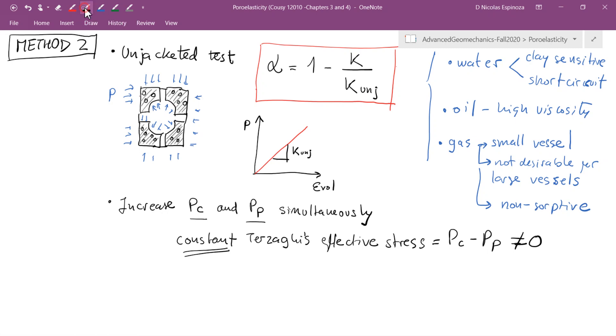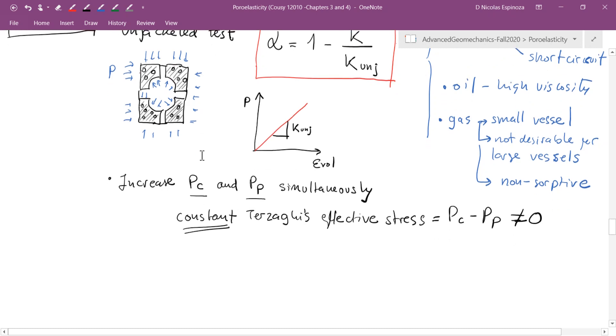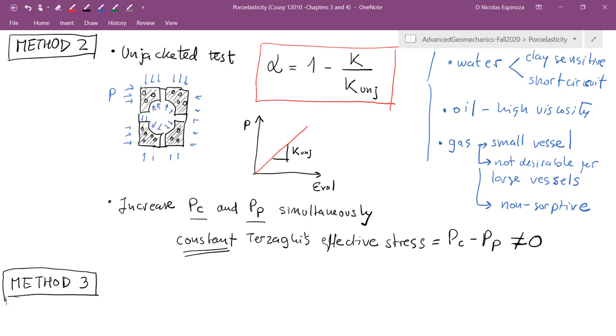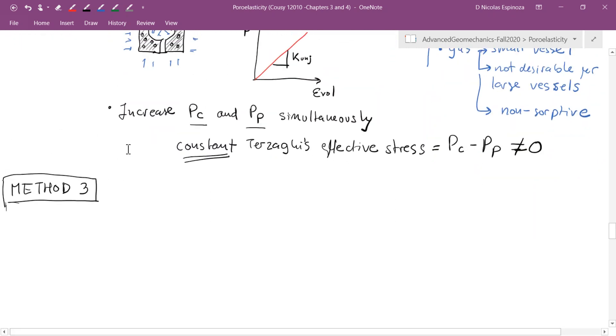This is method number two — a bit more complicated than the first one, requiring actual laboratory testing. Let's see method number three, which is my favorite. In method number three, we take advantage of the first equation of poroelasticity, which tells me that mean stress equals the bulk modulus times volumetric strain minus the Biot coefficient times pressure.